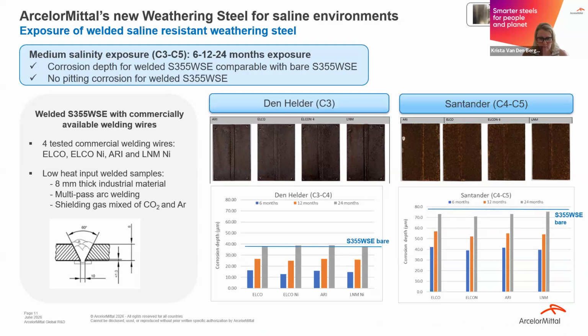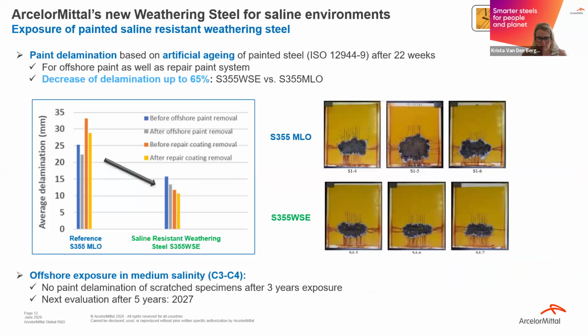If we move then to the painted material, we see that in an outdoor exposure running for now 3 years, we don't see corrosion in the defect that we created in the coating. In an accelerated test, we have faster results, and this test has run for 22 weeks. In the upper part of the images, you see the reference structural steel, and below we have our saline-resistant weathering steel. So if you use it in painted condition and you have a defect in the paint, you see that you have less delamination when our saline-resistant weathering steel is used, which is a promising result in case the material or the structure needs to be painted.